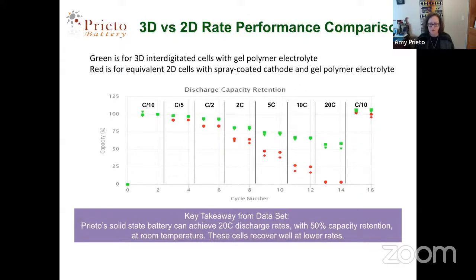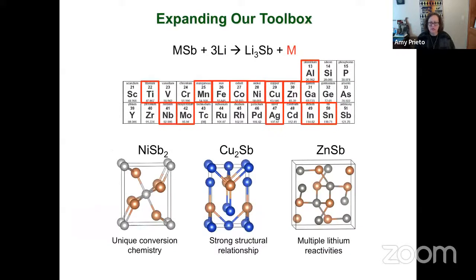I do want to be very clear, though, for these batteries, we did gel the polymer with a liquid additive, and that's to enable low temperature performance. But what you can see from this is that the green battery, the 3D battery, does a much better job of retaining capacity at very high rates. Both architectures recover well, so the chemistry is pretty robust, but what you're seeing here is the effect of the architecture. So just to wrap up, that's a new way of putting together materials.